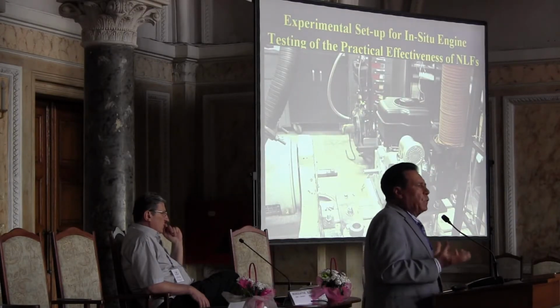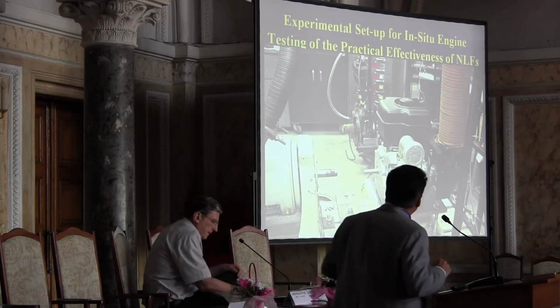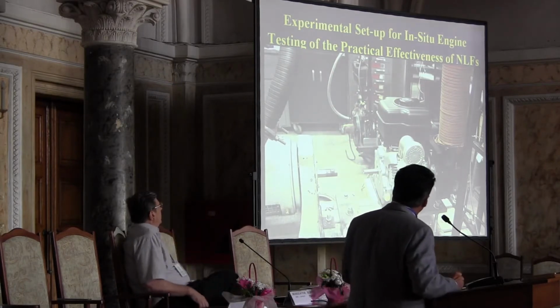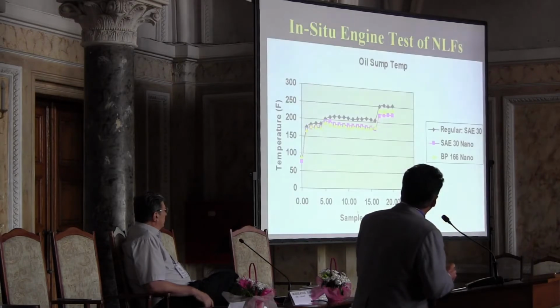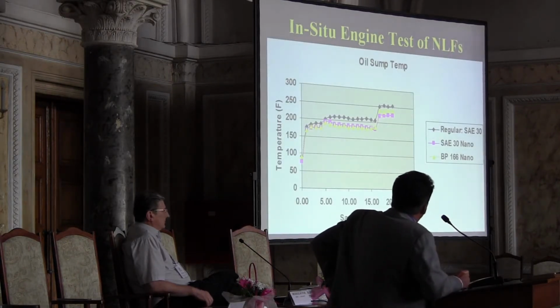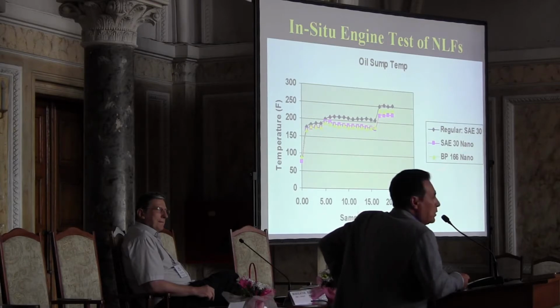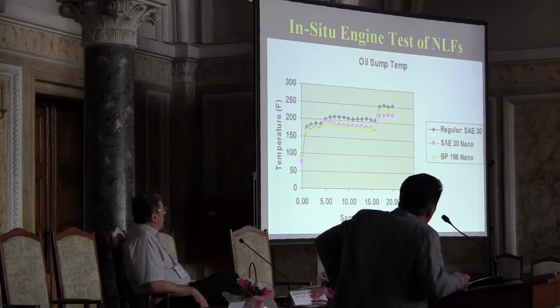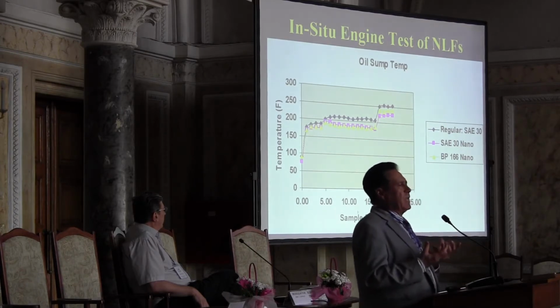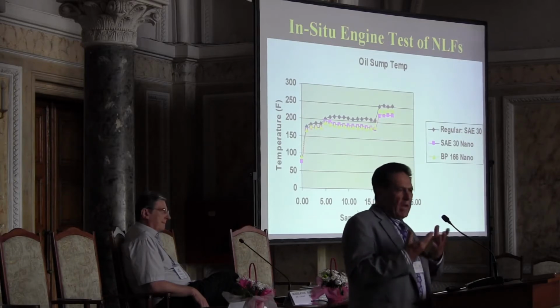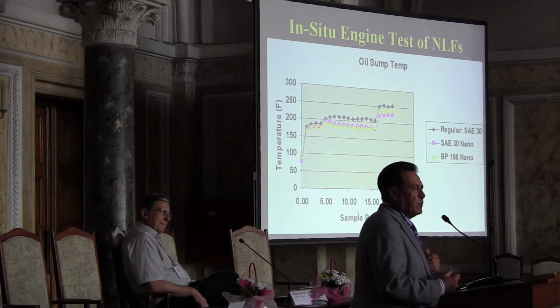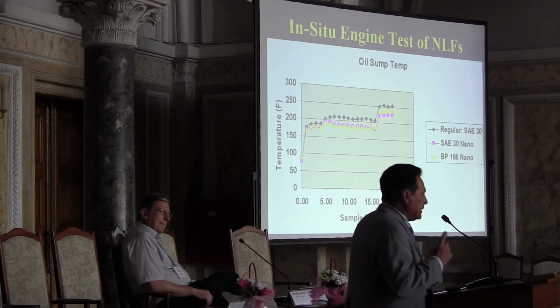So how do these fluids behave? We put them in practice, and this is the application. We are using a lawnmower, okay? And we are loading this lawnmower with the typical oil, that is an SAE30, and the SAE30 Nano, and the BP166 Nano. So this is a commercial one that has already some additives, and if you are cranking the engine, what you are seeing is that the temperature of the engine, when you are using a nanofluid, is always much lower, which is explained by the higher thermal conductivity and the higher lubricity in the material.